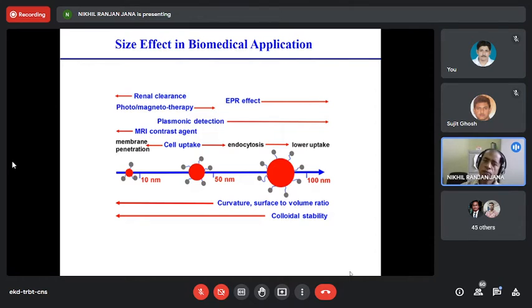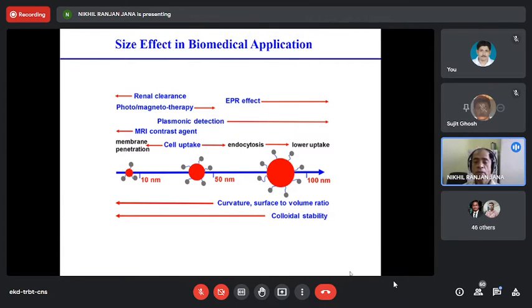We have to understand the size effect when we want to use them in biomedical application. Size is important. Size, surface chemistry. Here we are mostly showing the size. If you want renal clearance, meaning you inject something in the body, image, do some function, and then everything should be cleared from the body, for that you need a very small size, less than 10 nanometers. If you want photo or magnetotherapy, magnetic field based or light based therapy application of nanoparticles, larger size is better for therapy, but smaller is better for clearance from body, clearance from cell. So depending on the requirement, you have to design.